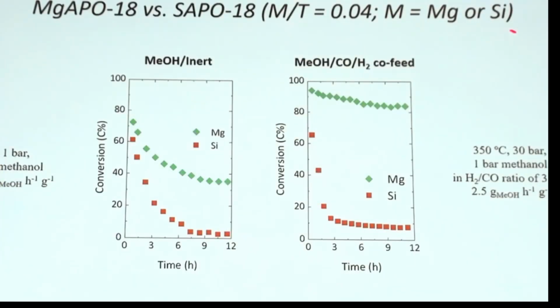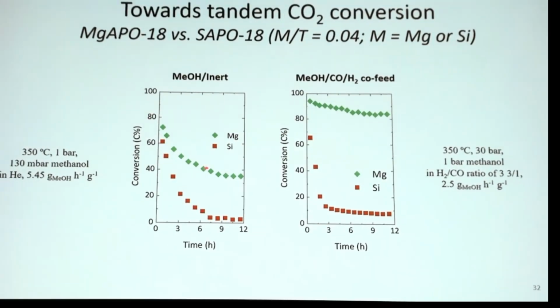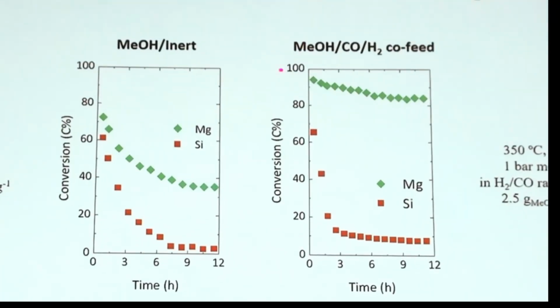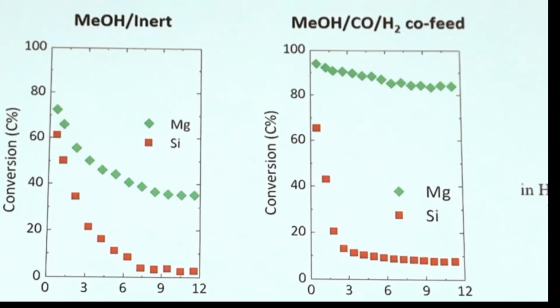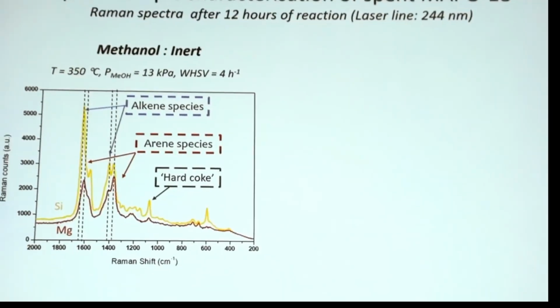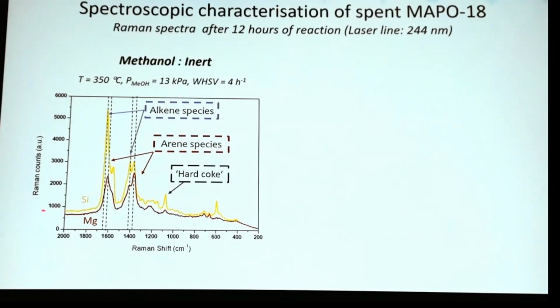So we went back and made new catalysts, with the same abundance of magnesium and silicon, and compared again under methanol and co-feed conditions. And we see the same as before. The silicon catalyst is deactivating much faster than the magnesium AlPO, and even more so under co-feed of methanol, CO, and hydrogen. In yellow here, this is Raman spectra after testing of the silicon version, and we see that there is a high abundance of hard coke in this catalyst, which can explain why it is deactivated after 12 hours on stream. We have much less of that in the magnesium catalyst, but we also see some occluded alkene species in the silicon material, less in the magnesium AlPO, but we have more aromatics in the magnesium AlPO material.